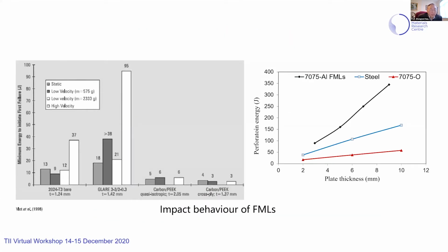Now, I'll talk a little bit about impact behavior from previous studies. This is the minimum energy to initiate first failure for the materials panels. We can say this is 95 joules for fiber metal laminates, layup 3-2, which is much, much higher than other materials like pure aluminium 2024 T3, and also carbon fiber PEEK, which is a pure composite.